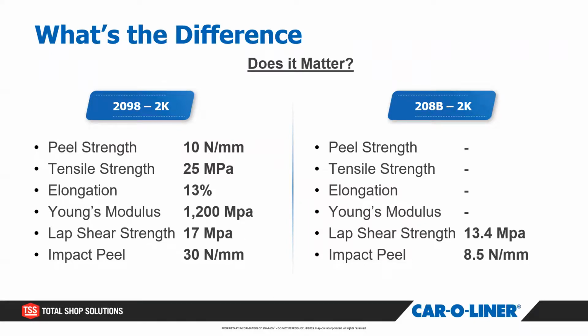But what's really scary here is the difference in impact peel. When we talk about that sudden crash scenario, like that BMW that got rear-ended, the 2098 2K adhesive is rated at 30 Newton per millimeter, but the 208B panel bond adhesive is only rated at 8.5 Newton per millimeter. So the crash durable 2K 2098 adhesive is over 3 times, almost 4 times as strong when you compare across. It doesn't so much matter when you glue it together, the adhesive sticks, everything's good. It's when the car gets put into a crash scenario that the joints can fail.